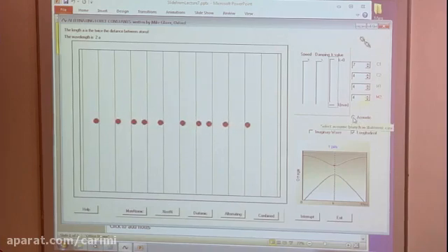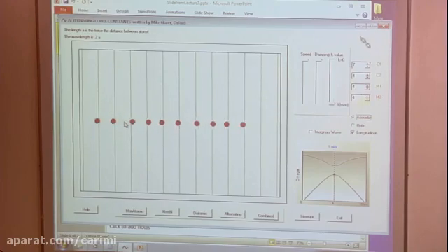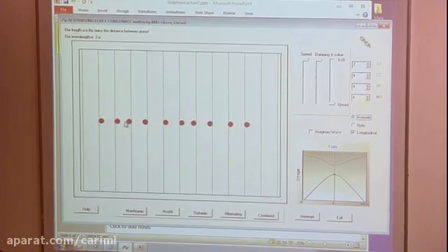Now, if you switch from looking at the optical mode at the zone boundary to the acoustic mode at the zone boundary, it looks extremely similar, but it's lower frequency here. But you'll notice it's the other spring that's now getting compressed. You still have one unit cell moving in one direction, another unit cell moving in the opposite direction, but now it's the opposite spring, the kappa 2 spring, which is being compressed rather than the kappa 1 spring.